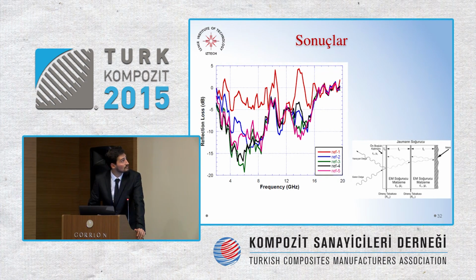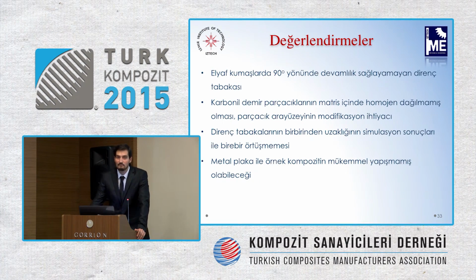The result. At first, 15 decibels was not possible to see, but later we have 20 decibels. Why? Because of the thickness. Thicknesses were very finely tuned. But of course there are differences between models and experimental studies. Why? Because with models we think of our layer as a continuous material, but on unidirectional fibers it might be continuous at 0 degrees, but at 90 degrees they are not continuous. This might be the reason.